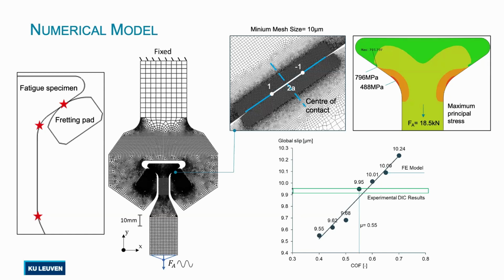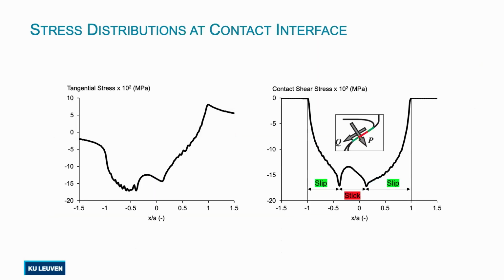And for the accuracy of the model, to rely on these results, we also did some calculations. We got the global slip amplitude, taking the average displacement here, and then we compared that with the experimental DIC results to make sure that we are using the correct frictional parameters. Then we did some simulations and found out that 0.55 is the correct, or at least a reliable, coefficient of friction that we can use.